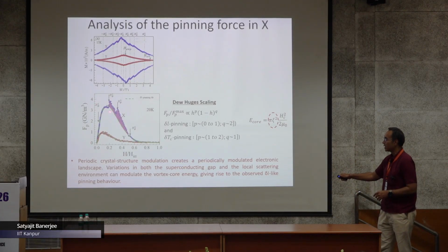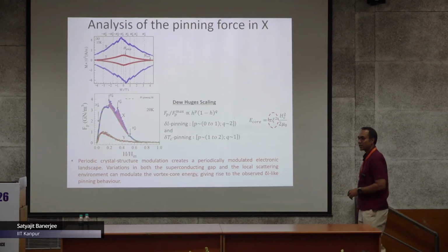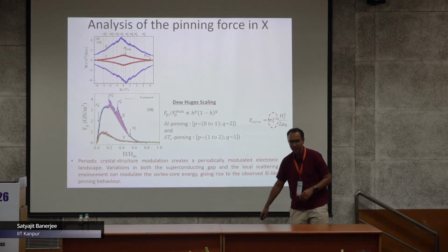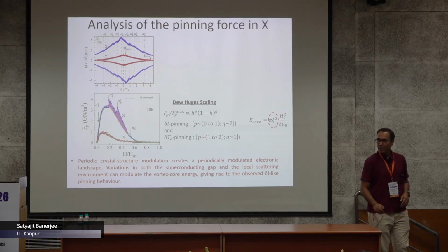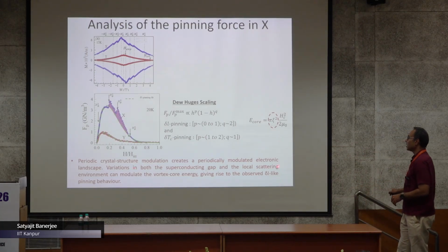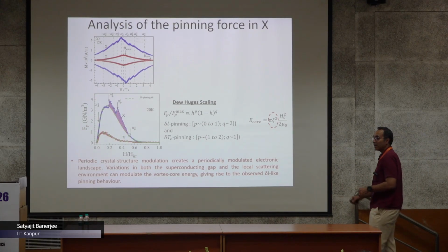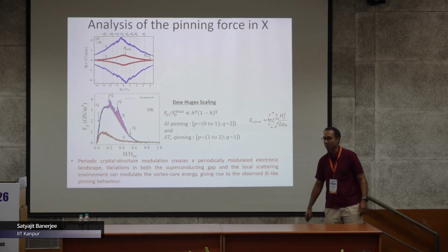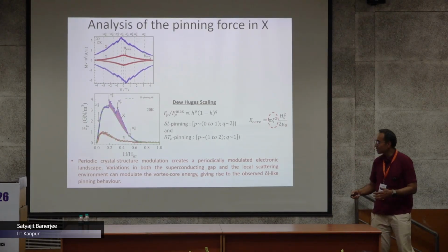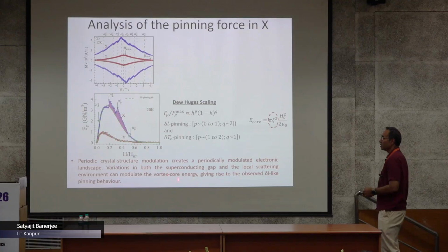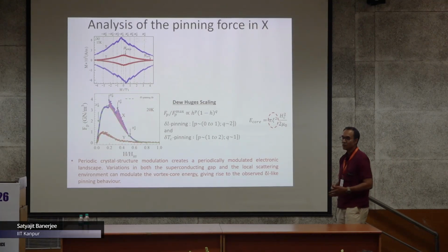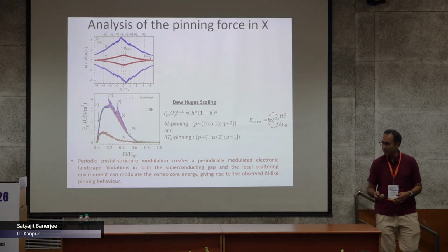Over and above the delta L pinning mechanism, you see these fluctuations corresponding to the commensurate state. It looks like the modulations in the crystal are periodically modulating the electronic landscape inside the superconductor, and these variations are coupling and varying the vortex core energy to give rise to periodic pinning inside the crystal.